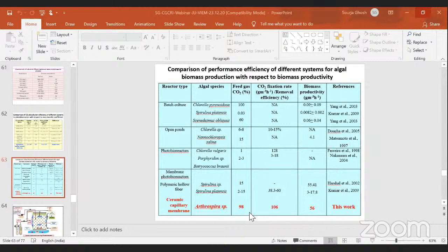So this also shows that the ceramic capillary membrane, we have introduced this first time globally. This indigenous ceramic hydrophobic membrane based photobioreactor process has been established for the first time, and this shows that Arthrospira species can be produced at a high productivity rate.